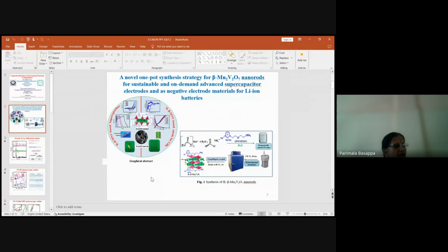So metal vanadate nanomaterials can be used for energy storage devices due to their high specific area and excellent electrochemical properties. So this is the schematic synthesis of our material. We have taken manganese vanadate and ammonium metavanadate in the ratio 1:1, without adding any ionic liquid, in 50 ml of water in a Teflon liner. First, we magnetically stirred for about 20 minutes, and then took it in an autoclave in a Teflon liner and exposed it to hydrothermal treatment, heated at 170 degrees for 20 hours. Then the product was centrifuged, washed, and dried at 80 degrees centigrade for 4 hours.